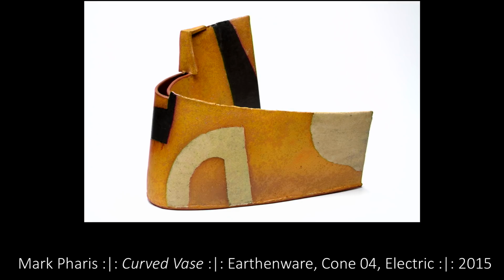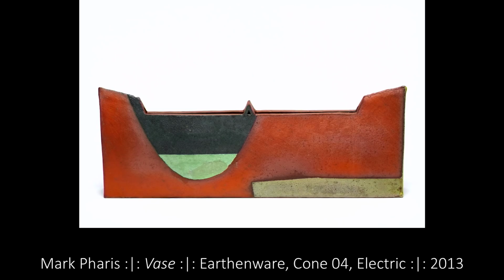Breaking Terra Sigillata rules, Mark Pharis often mixed his Terra Sigillata by eye, following the approximate 1 part clay to 2 parts water, more or less. After bisque firing his work, Mark applies a flux-containing low-temperature slip. Then he sprays on 3 layers of Terra Sigillata. The additional flux material in the slip allows the Terra Sigillata to stick on the bisque-fired work. And while he experiences some variation in color over time, potentially due to the difference in specific gravity, this is a variation he prefers to keep in his process.